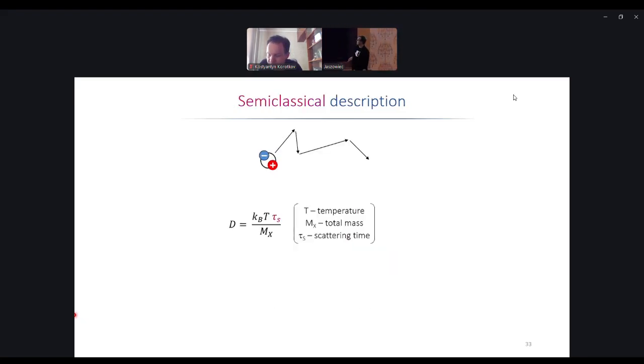And the semi-classical description one can also use to try to connect the scattering rates to the diffusivity. How can we try to access exciton scattering optically? If we're interested in this tau s, what type of experiments come to mind? If we try to find out the scattering rate of excitons with phonons, impurities, electrons, what do we need to do? Measure dephasing. This is the best way to do it. How do we measure dephasing?